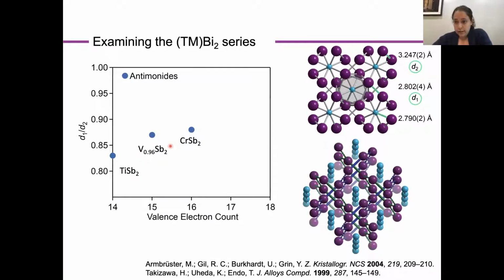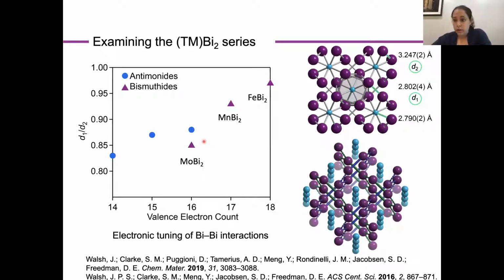the distortion lessens. And if we expand our focus to the bismuth versions of the structure, we see that the trend holds, with molybdenum bismuth being the most distorted version of the structure compared to the manganese bismuth and iron bismuth versions of the structure, which have been previously reported at high pressure, as I mentioned on a previous slide. And so this is quite interesting because oftentimes the structure is discussed in terms of somewhat strict steric tolerances. And so seeing the importance of electronics on the resulting structure, I was wondering why this might be the case.